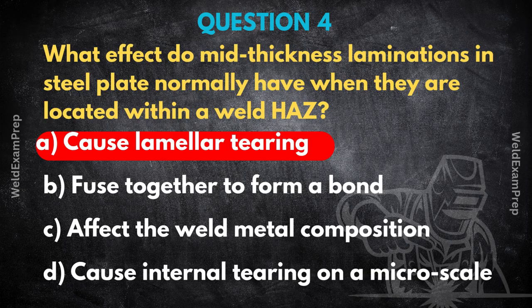What is it exactly? A mid-thickness lamination is basically a flat planar defect. Think of it like a thin pancake or a layer inside the steel plate running parallel to the surface. It's usually from impurities or voids in the original steel ingot that didn't fully weld together when the plate was being rolled. And crucially, that defect creates a weakness in one very specific direction.